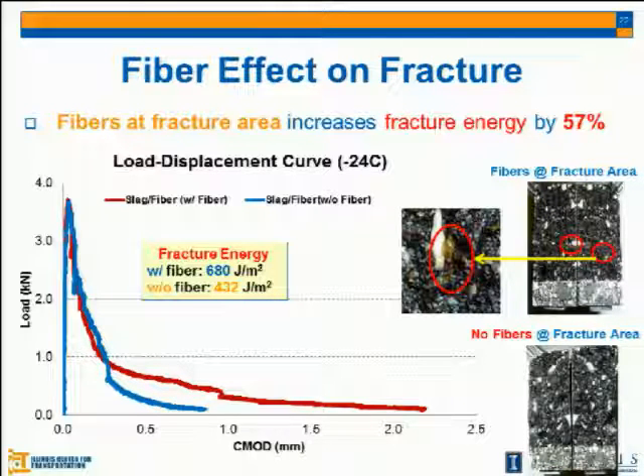But we added the fiber in this mixture at around 0.05% by weight of asphalt mixture. This is the weight or volume? Weight. So in the plant, when they produce 1 ton of the material, they put in 1 pack of the fiber. 1 pack has 1 pound of fiber. So it's 0.05% of the fiber. This is recommended by the companies actually. So we use the same percent, the same amount of fiber in the mixture.